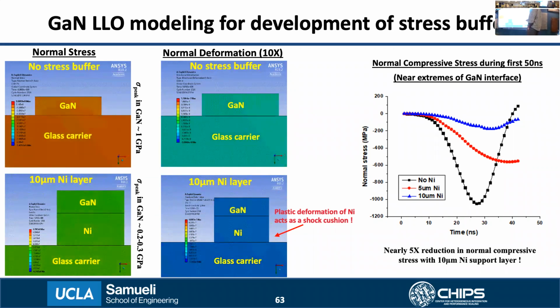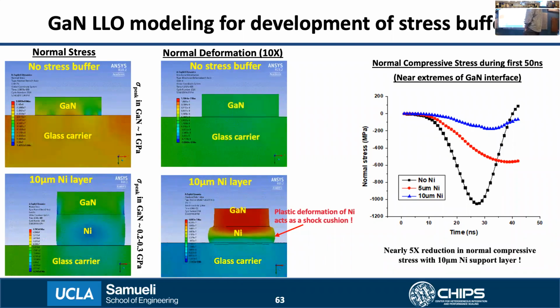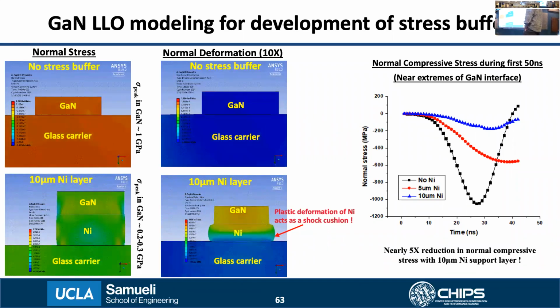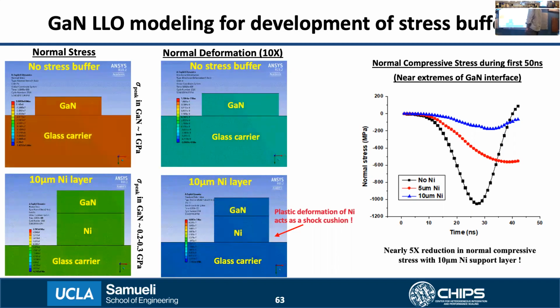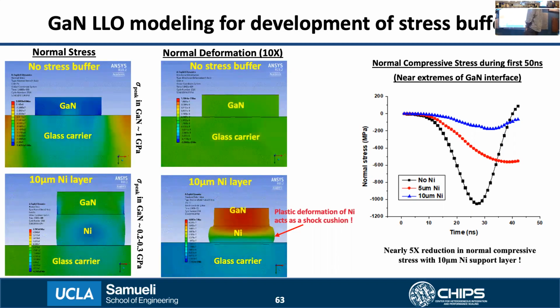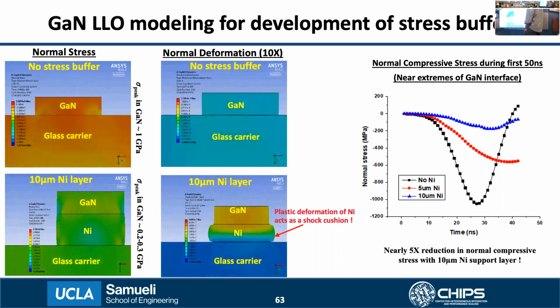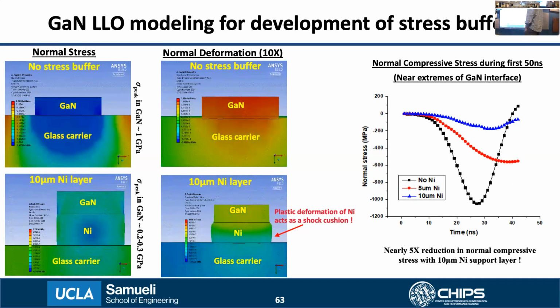The key point here is that during this process, when we don't use any nickel layer, the peak stress in the GaN is around 1 gigapascal. But when we use a 10 micron thick nickel layer, the peak stress falls by around 5x, to around 0.2 to 0.3 gigapascals.